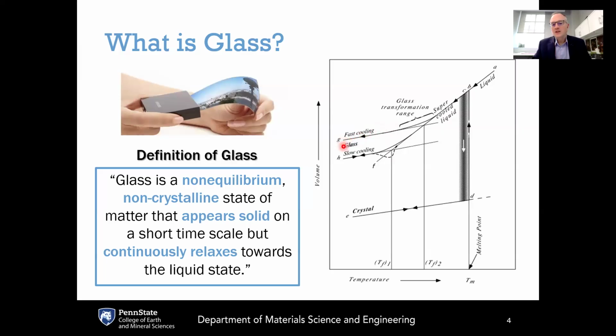And when that happens, we get the glassy state, this vitreous state known as glass, that has the structure of the supercooled liquid because the structure of the supercooled liquid was frozen into the glassy state. So the structure of a glass is akin to that of the liquid. But if you were to say bang the glass with a hammer or drop it, what you will see is that its mechanical response is a lot more like a solid. So a glassy material has certain properties that are like a solid, like its mechanical response. It has other properties that are like a liquid, such as its liquid-like structure. And it is continuously connected to the supercooled liquid through this glass transformation range or glass transition range.